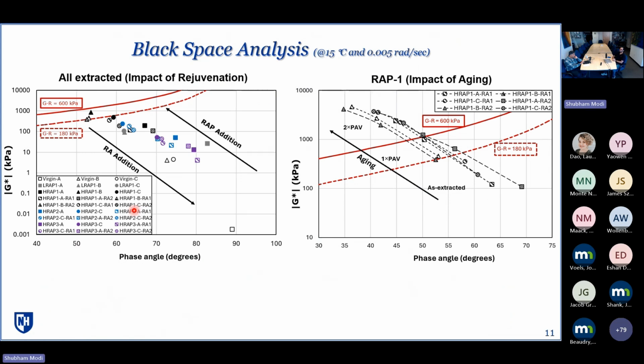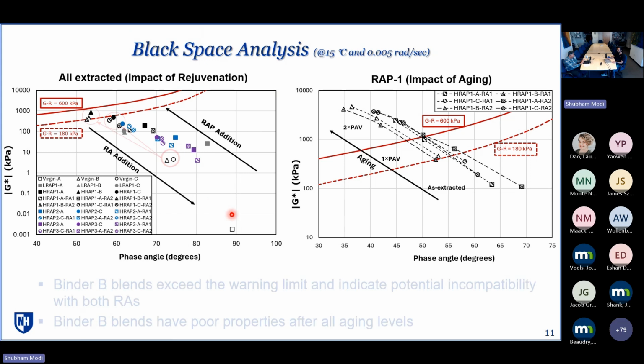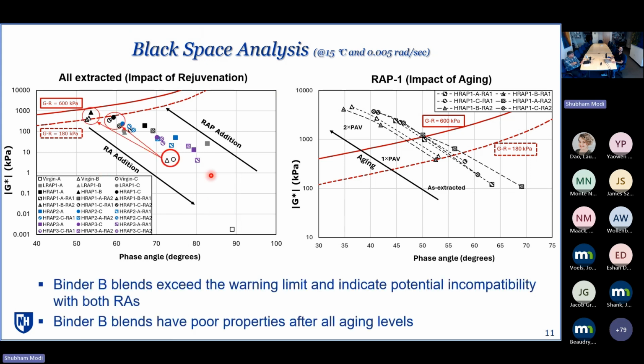Then discussing the black space results, here we can see that in general, the addition of the RAP resulted in moving the points towards the left top corner, whereas the RA addition reversed this process and moved them to the bottom right corner. And as we can see in this plot, triangles are representing binder B results and circles are representing binder C results.